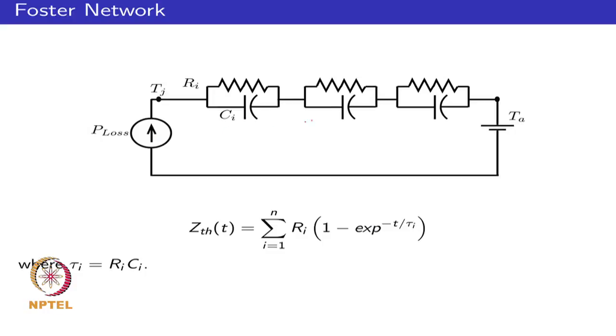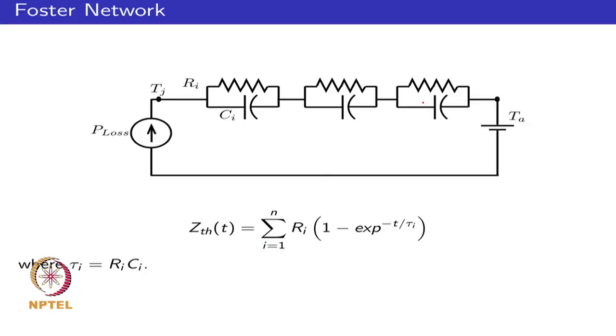The number of RC elements is typically between 2 and 6. The number of elements can be higher to get a better approximation to the thermal response characteristics of your measurements with your model of the thermal system. The data sheets typically provide the Foster network parameters, or some data sheets may just provide the transient thermal impedance curve. And we saw that connecting the module together with the heat sink, one has to make transformations between the Foster and the Cauer networks.